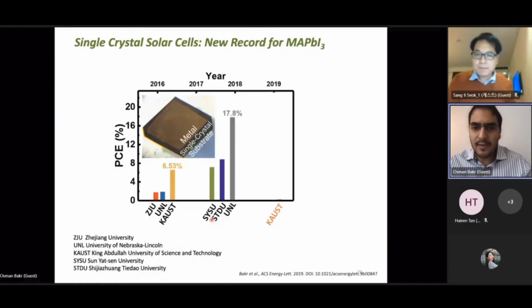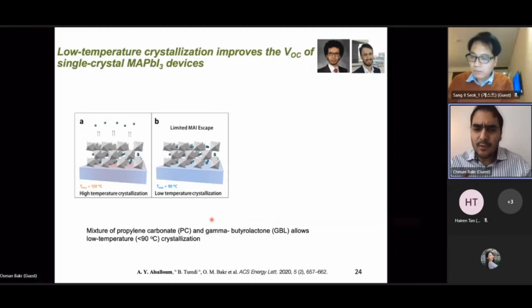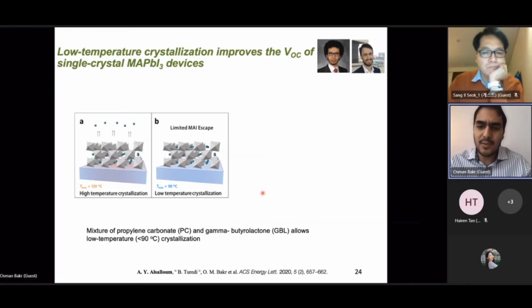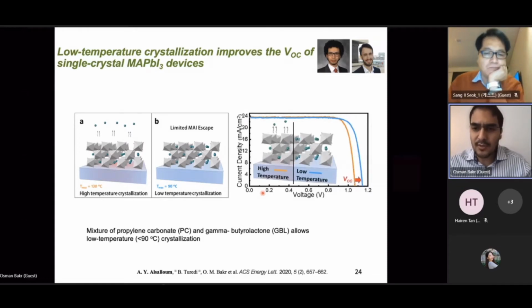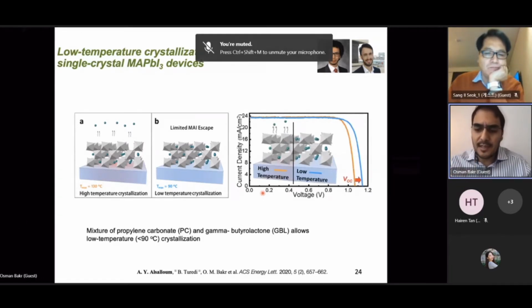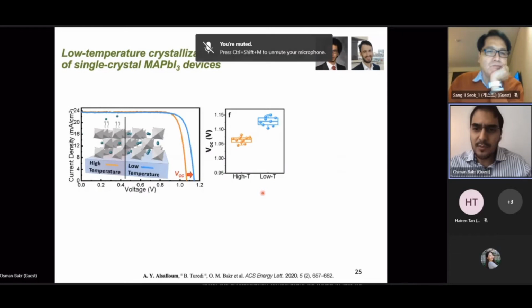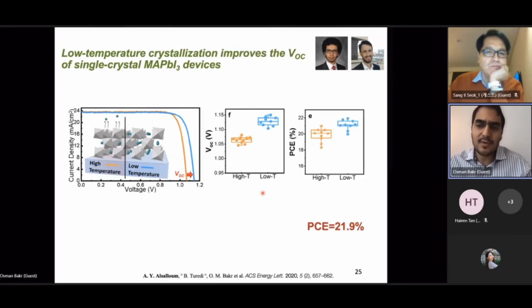So the second step for us was, can we improve this process further? Because we realized that the crystals were being grown at relatively high temperatures, 100 and something degrees, 120 degrees. So we started looking at different solvents, and can we reduce the crystallization temperature? And what we found is that if we mixed GBL with propylene carbonate, we could lower the crystallization temperature. In fact, we found that we could reduce the amount of lead iodide that forms on the surface of the crystal, and thereby improve the interface, improve the VOC of the crystal, and we can improve the efficiency almost to 22%.